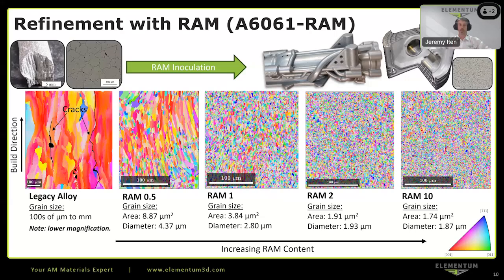I think that's the big thing about the RAM process. Because you're generating this very fine equiaxed microstructure, you get very consistent properties. With a columnar type structure, one of the issues is you'll have different properties in the Z or growth direction versus in the XY or in-plane direction. Whereas with the RAM process, because the microstructure is so consistent, the properties are also very consistent across different directions.